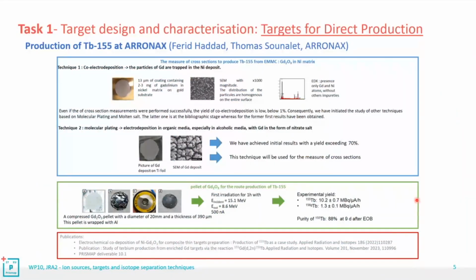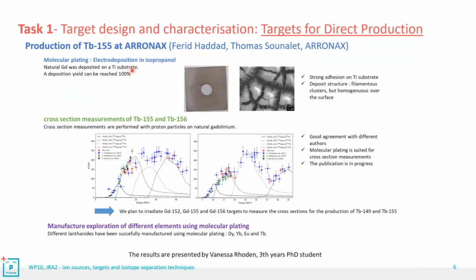I would like to go on describing the important research activities done by the Aronax group, in particular for the production of terbium 155. They are deeply involved in the research activities for both thin and thick target productions. In particular, I would like to highlight the work they did on molecular plating technology. They deposited natural gadolinium on a titanium substrate, and this is the result shown by these 2 figures. Then in a second step, they made cross-section measurements, and here you can see in red the measured points that are in good agreement with the different references that we found in literature.